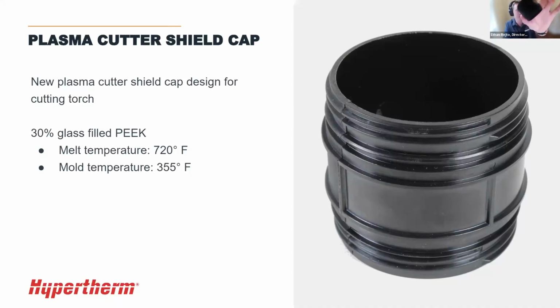They were trying to test out these new components, but these, again, were being molded in a 30% glass-filled PEEK, which is a very, very abrasive, high-temperature material. This thing is so stiff, as you can imagine, because it's PEEK filled with glass fiber. The melt temperature of the material was 720 degrees Fahrenheit. The mold was actually being heated with oil to 355 degrees Fahrenheit. So aluminum obviously was not going to be an option here for their development tooling.